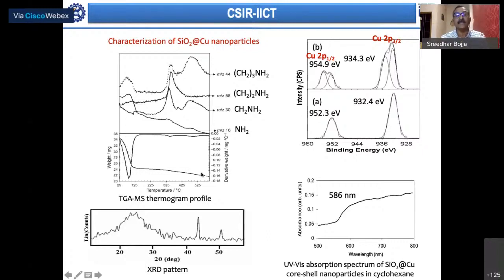Generally, small weight loss features are not clearly seen in thermogravimetric analysis, so people take a derivative of it. When you take a derivative, things become very clear, and this initial first step becomes very clear. But other than that, you see a small step around 300 or 400 degrees centigrade, which is due to the decomposition of the functionalized material present between the core and the shell.